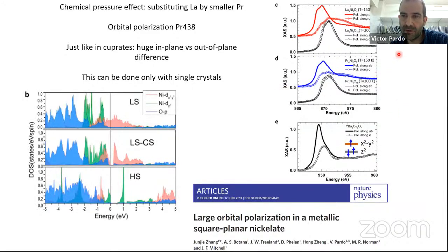These experiments of the spectroscopy were carried out by John Freeland, and what he saw is that you have a huge orbital polarization. This means that you can measure the spectrum in the AB plane and the spectrum along the Z-axis, and there's a much higher absorption for the orbitals in plane than the orbitals out of plane. And this is similar to what happens in the cuprates.